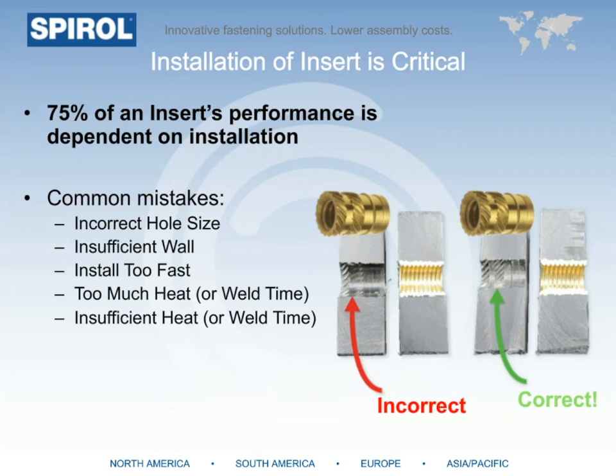As you can see in the incorrect example, the knurl's imprint in the plastic was very shallow, and there's no evidence that the barb actually engaged the plastic. Some common errors that lead to poor installation are listed to the left, but in this example, you can see that there was probably an incorrect hole size that was too large, not allowing enough plastic to flow into all of the insert features.